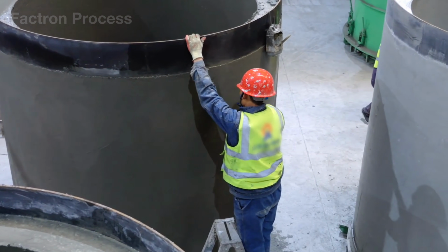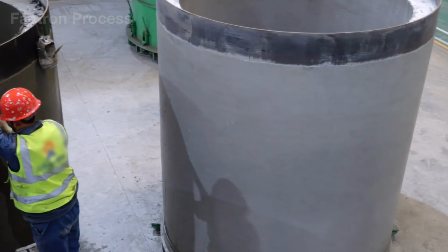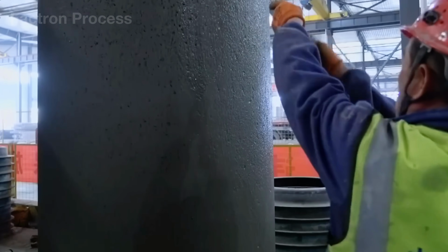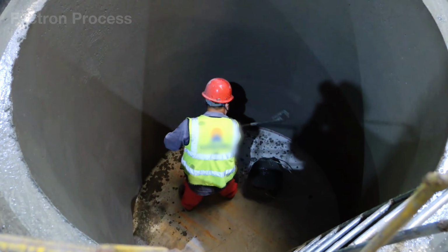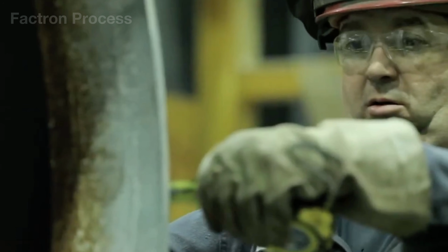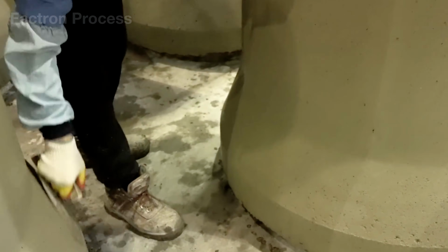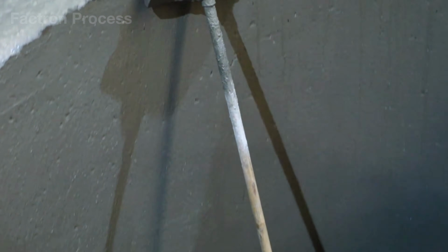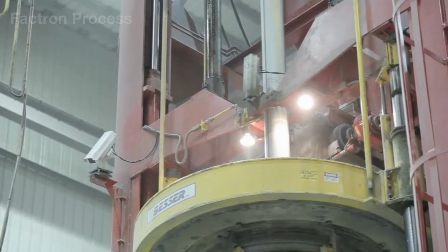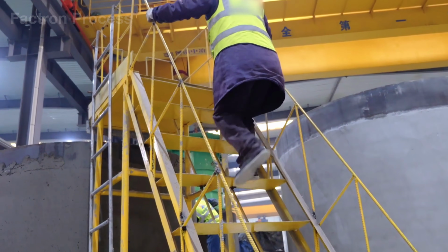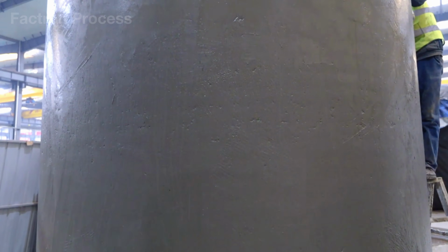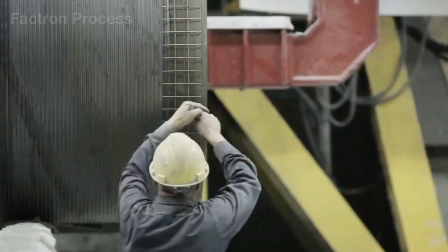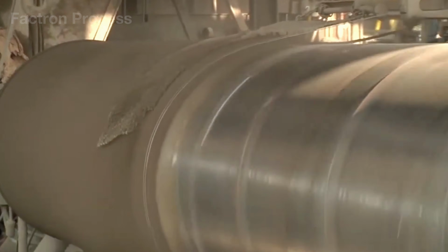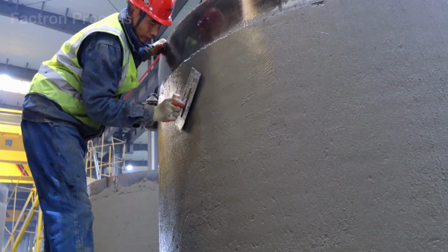Once the concrete has reached sufficient strength, each pipe enters its final examination before leaving the factory. Technicians slowly inspect the entire surface, from the outer wall and inner barrel to both joint ends, looking for small cracks, voids, chipped edges, or uneven concrete left behind after demolding. Products with acceptable surfaces then move on to dimensional inspection. Their diameter, length, wall thickness, and roundness are checked with specialized measuring tools. Every deviation must remain within the allowed limits, because even a slightly inaccurate joint can cause an entire underground drainage line to leak after installation.